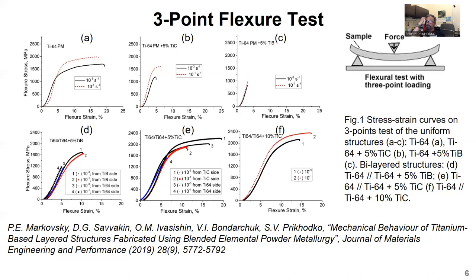However, we believe that the three-point bend test is the most relevant to anti-ballistic performance of armor. The top panel here shows result of three-point bend test of uniform structures, and the lower panel shows result of layered structures. We can see significant increase in flexure stress and flexure strain of laminates compared to uniform composite. And what is remarkable, compared to uniform Ti-6Al-4V as well. So we expect that laminates can demonstrate significant improvement in anti-ballistic performance compared to uniform structures.